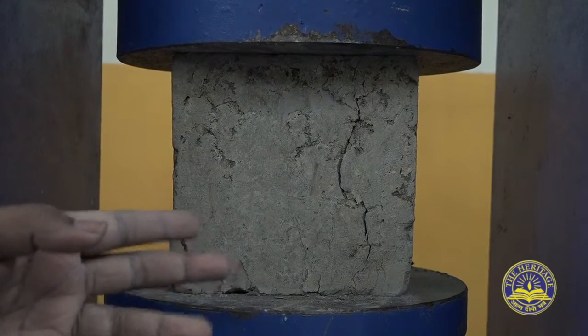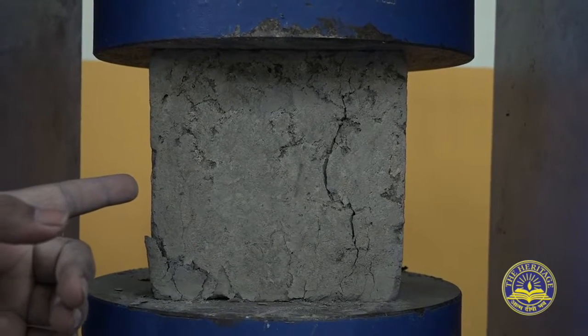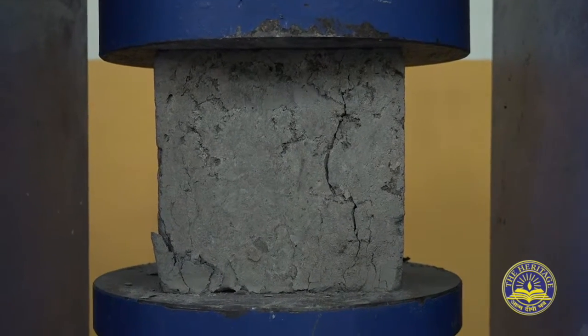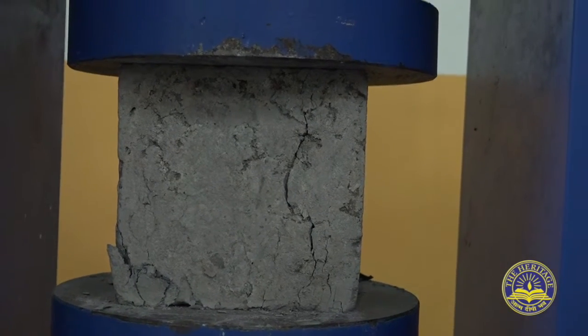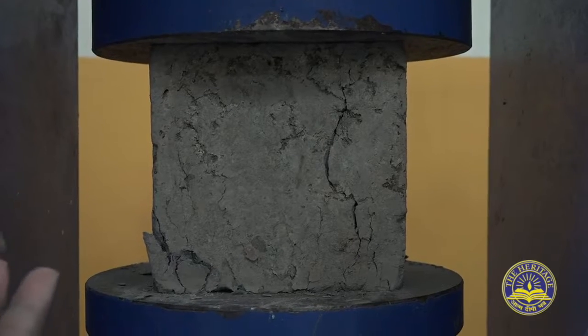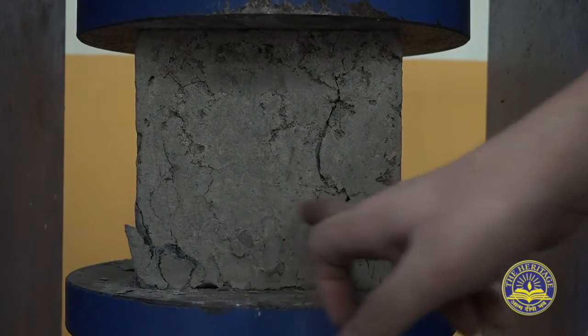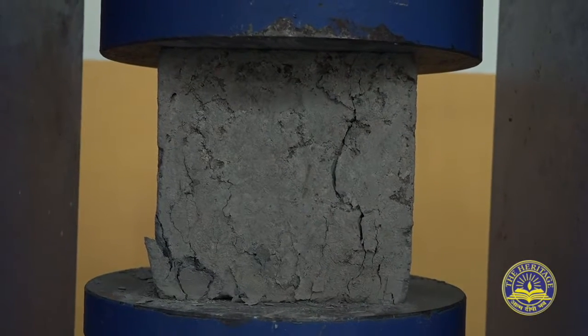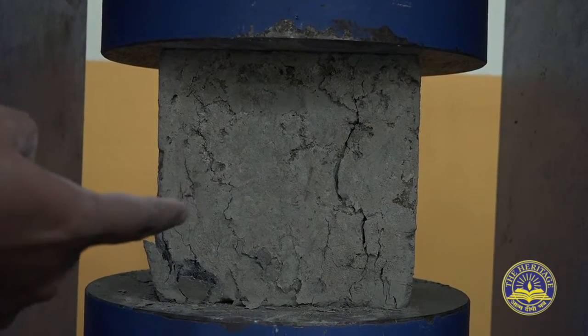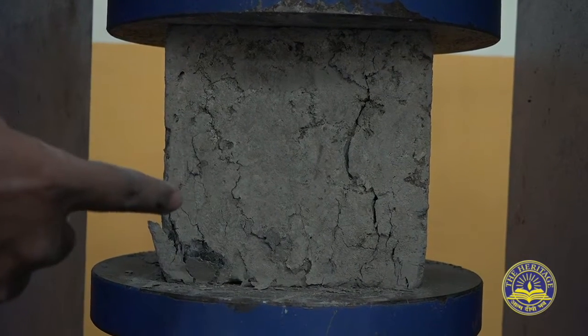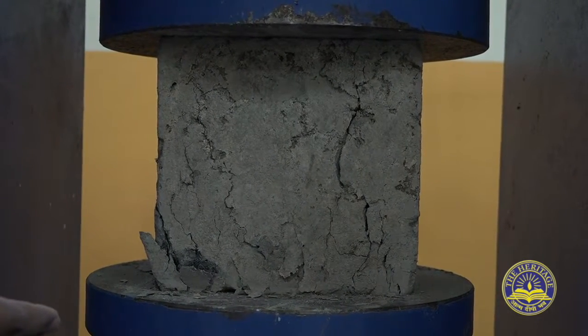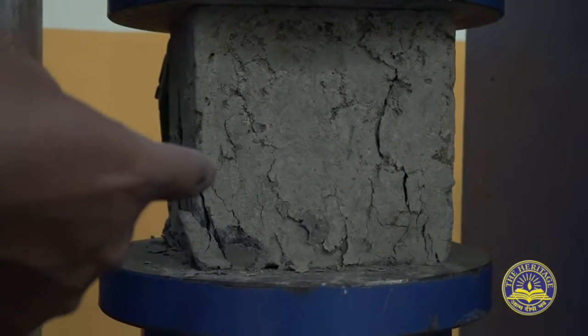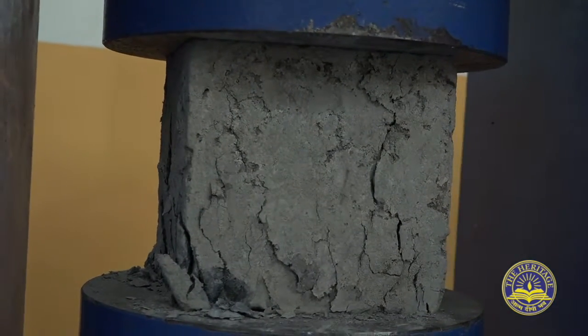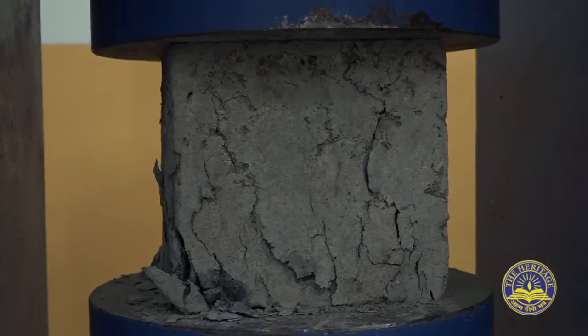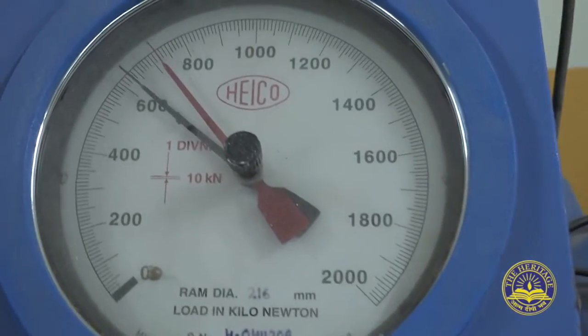See how the crack has been generated in the compacted concrete. See how the outward edges have started to rupture. Crack formation is taking place. See how the crack takes place here after a great loading. Slowly and gradually all sides of the concrete become crushed under a certain load. Now stop. Now the reading is decreasing.